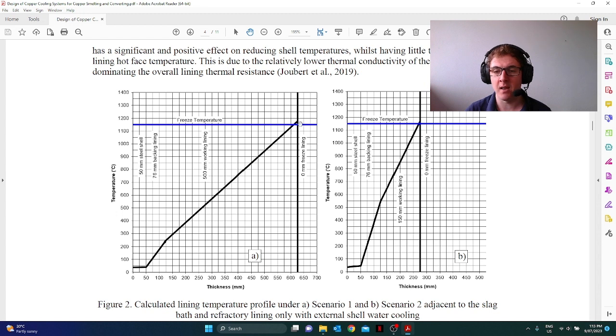You suck more heat out of the furnace, but when you go through the maths, you can see that the hot face of the brick still gets eroded away. And so from this, the driving force of the solution is here and not the slope. So sucking more heat out of the furnace, you can see here, does not lead to much slower refractory corrosion. It may have a small impact, but it's not really that big. It just changes the steel plate temperature, so you don't really get much benefit from it.